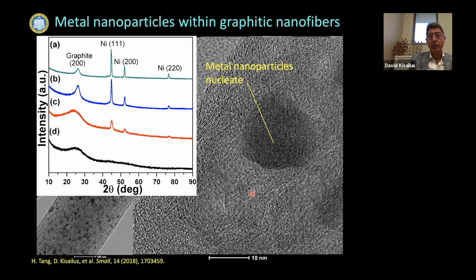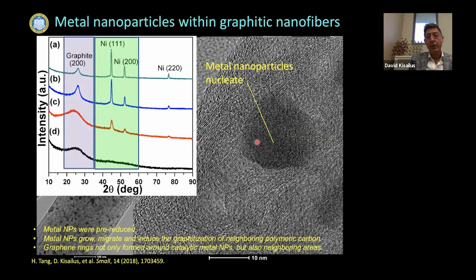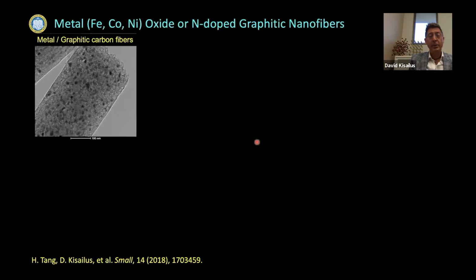And not only did the nickel form, but the carbon itself, we used the polyacrylonitrile, but at low temperatures, now we're finding as low as 400 or 500 degrees, we've now been able to graphitize the surrounding carbon, likely because the nickel itself, the transition metal, is a very good catalyst for graphitization. The mechanism we're still trying to determine.